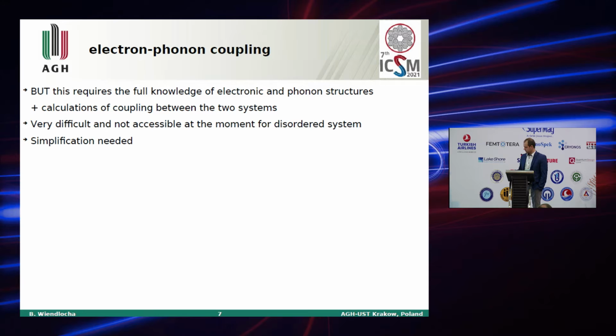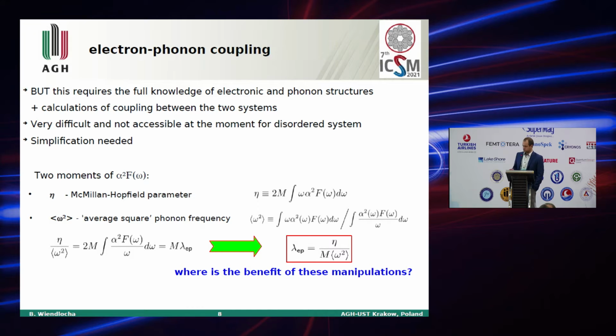But as I said, this calculation requires the full knowledge of electronic structure, phonons, and coupling between them. And for a highly disordered material, we have a problem especially of obtaining the knowledge about the phonon spectrum, since we would have to probe many different configurations of atoms in such cells. So in fact, we need some simplifications to tackle this problem. And to do this, we may take a look at the Eliashberg function again, and we can define two parameters which will be important in the next part.